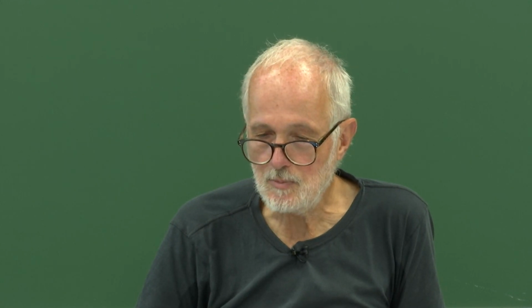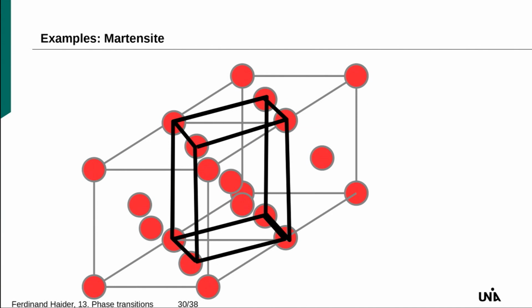There's one important point. This martensitic transformation is nearly volume conserving. If you have a volume conserving transformation, you can write down the transformation matrix and you find that there are invariant planes. And these invariant planes, that's where this shear takes place, and habit planes and so on.